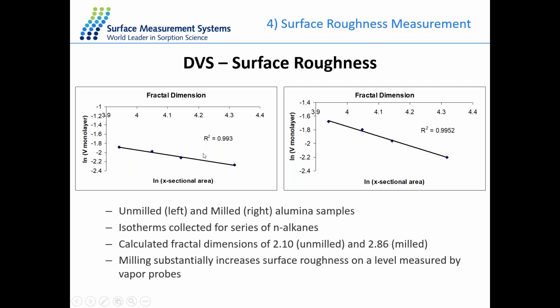So here, by plotting the monolayer volume against the cross-sectional area, from the slope here we can calculate that for the unmilled sample on the left-hand side, the fractal dimension value is about 2.1, and after milling, the fractal dimension value increased to 2.86. So the milling process induces an increase in the surface roughness for the alumina sample in this case.